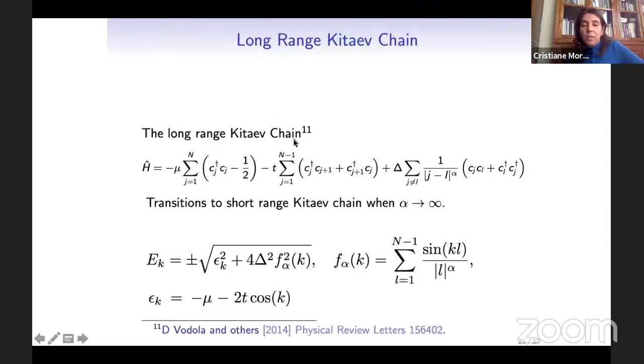Until now, I told you about the Kitaev chain, but we could look at a particular case of the Kitaev chain, which is the long-range Kitaev chain, where now, instead of getting pairing at nearest neighbors I and I plus 1, we could get pairing at neighbors J and L, which could be at any distance. We will consider that this pairing is getting attenuated by 1 over J minus L, where J and L are the sites which are interacting to form the pair, to the power alpha.